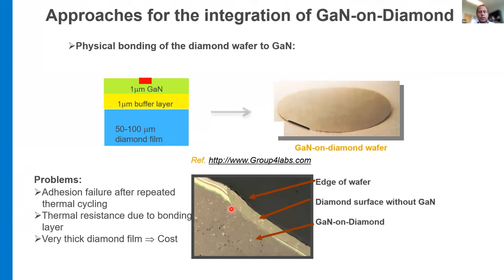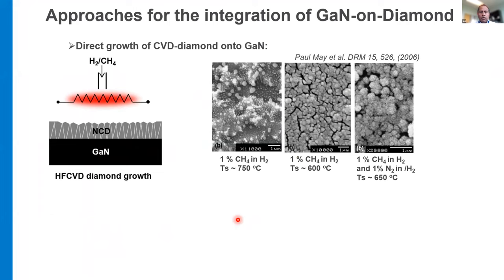And also in this case, you have to grow a film about 50 to 100 micron or even larger. So the cost, I think, is also an important factor here to grow such a thick diamond film. So there are various approaches people have tried to directly integrate diamond onto the gallium nitride by using a CVD process. In this case, they tried to deposit directly by using hot filament CVD,